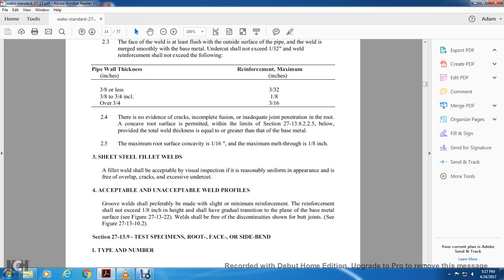There's no evidence of cracking, incomplete fusion, or inadequate joint penetration of the root. The concave root surface is permitted within the limits of Section 27-13.8.2.2.5 below, provided the total weld thickness is equal to or greater than the base metal. The maximum root surface concavity is 1/16 of an inch. Maximum melt-through is 1/8 of an inch.